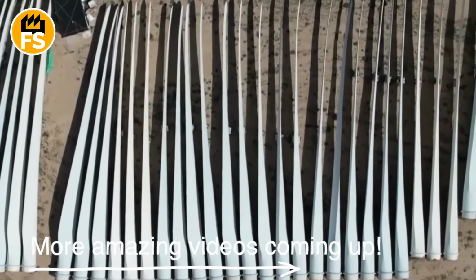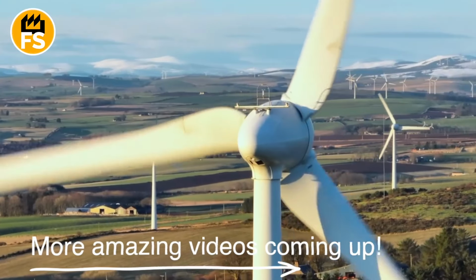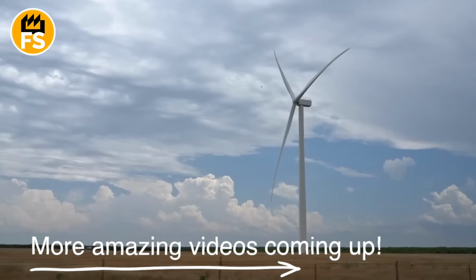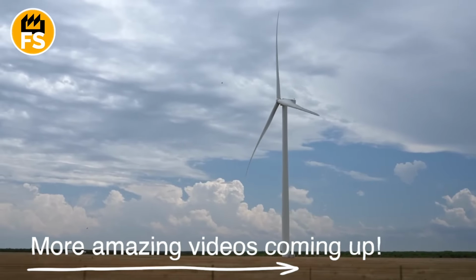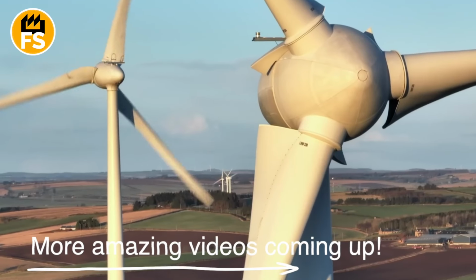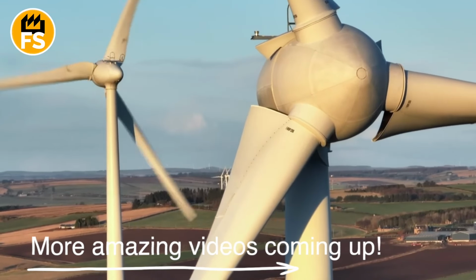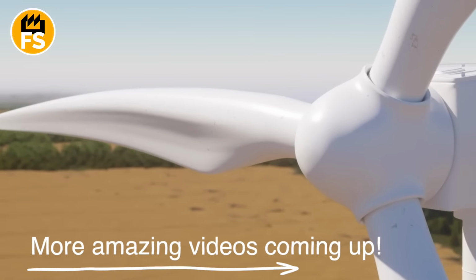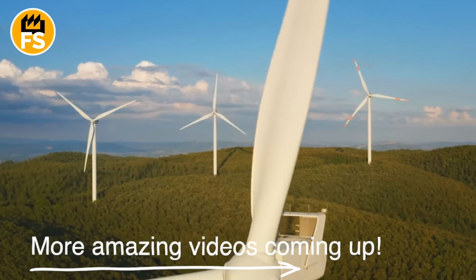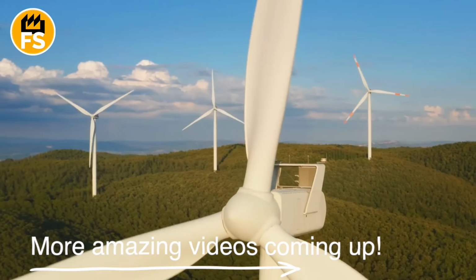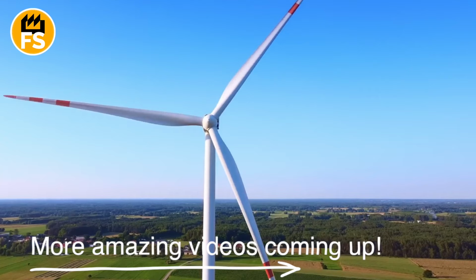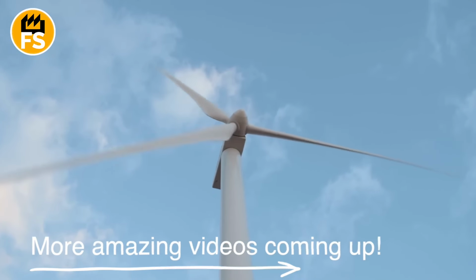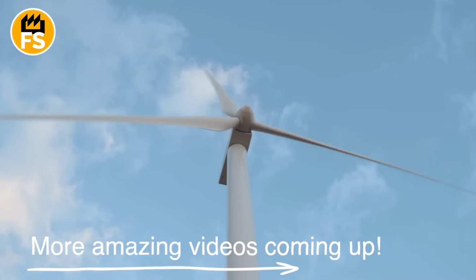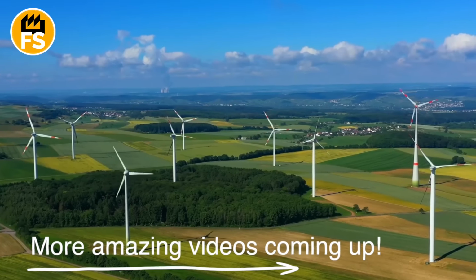The tips of the longest blades can reach rotational speeds of 180 miles per hour. Though they don't exceed the speed of sound, this requires the blade tip to be perfectly designed and protected from erosion. An ordinary raindrop hitting the blade at such speed has destructive force similar to sandblasting. This forces manufacturers to develop high-tech but expensive protective coatings for blade leading edges.